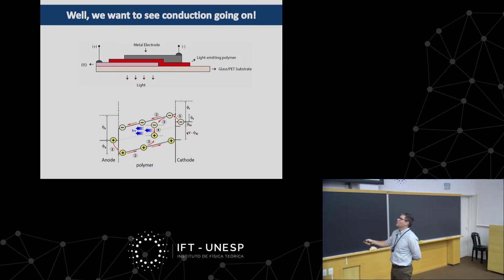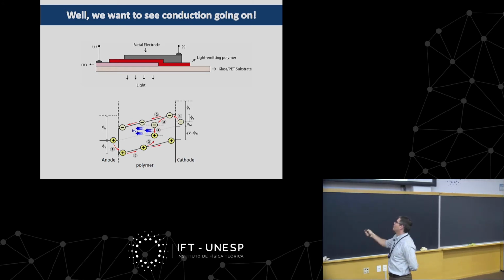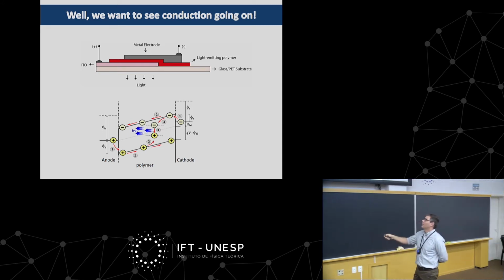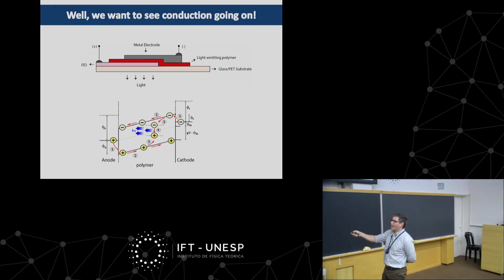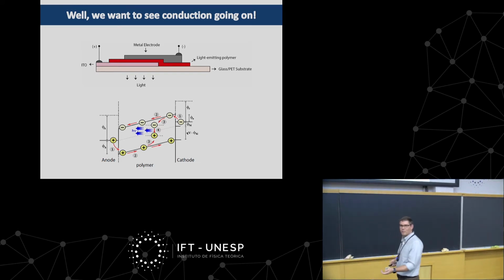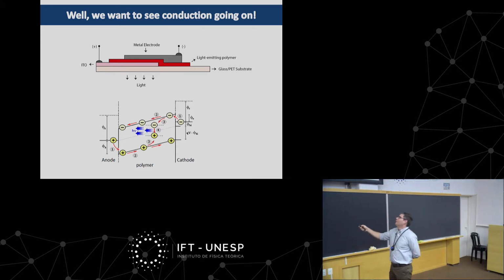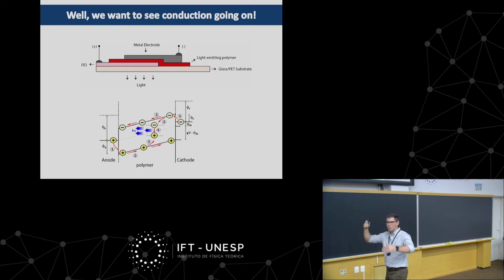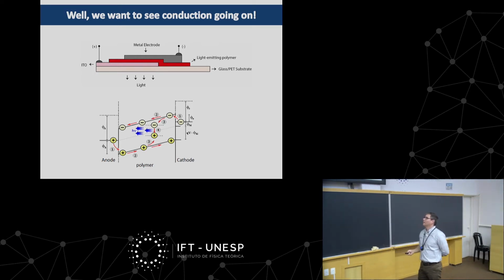So here is the anode, which is basically the ITO, the oxide. So here's the work function, and this is basically the valence band. And the way it works, when you apply a potential between your anode and cathode, the cathode being the metal electrode, holes, basically the vacancy of an electron, are injected into the valence band. You can think of an electron being extracted from the valence band by that particular metal. And at the opposite electrode, an electron is injected into the conduction band.